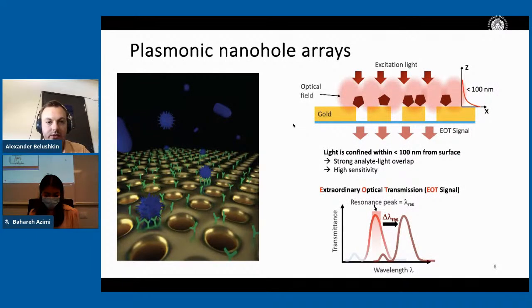As I mentioned, the technology is based on so-called plasmonic gold nanohole arrays, which are essentially millions of nanoperforations in thin gold metal films that enable so-called extraordinary optical transmission, which is light transmission that is much larger than that predicted by classical diffraction theory. When we shine excitation light on the surface of the nanoholes, it excites so-called plasmons, or electromagnetic oscillations, in the gold film, and these oscillations translate to a resonance peak in the far field. Because these resonances are highly sensitive to refractive index changes of the interface, we can observe it as a resonance peak shift, just like an SPR in the previous talk.